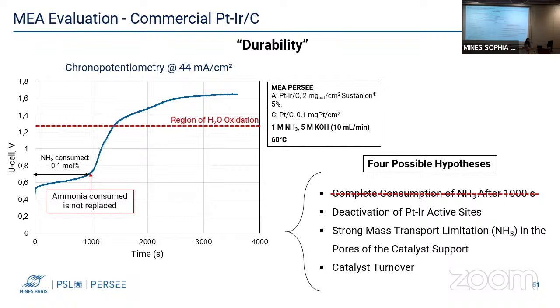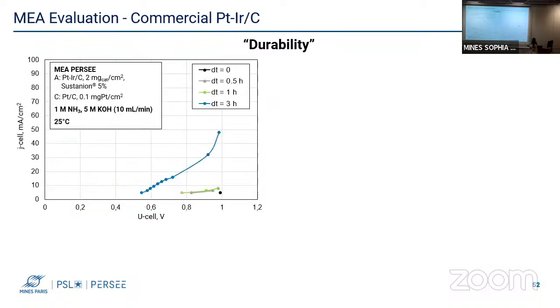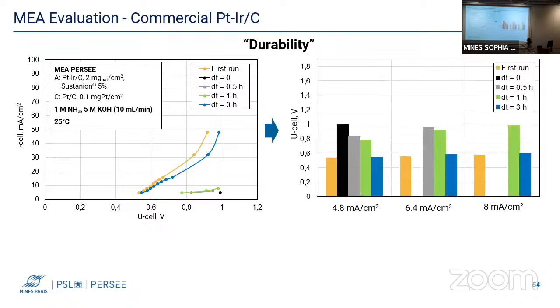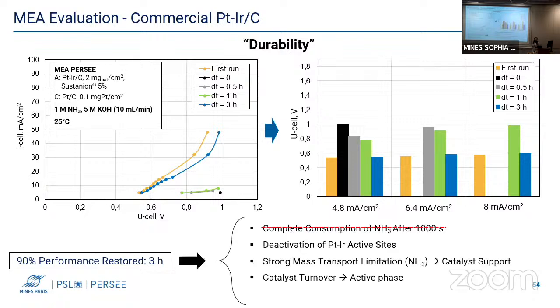In order to understand more, we conducted different runs at successive time intervals chosen to be between 0 and 3 hours. A DT of 0 means that the 2 runs were conducted successively. And we compare our data to the initial run. This graph shows that after 3 hours, it was possible to recover 90% of the performance of the MEA. And by going back to our hypotheses, it was possible for us to eliminate the first one.